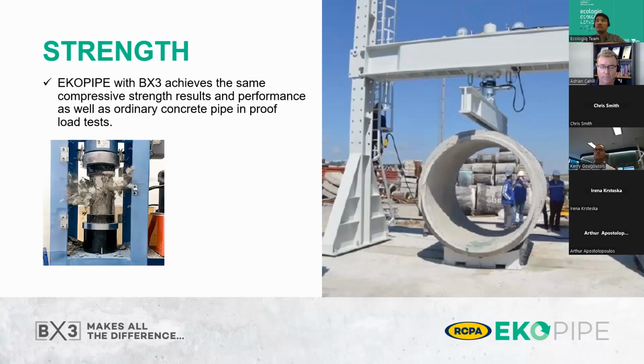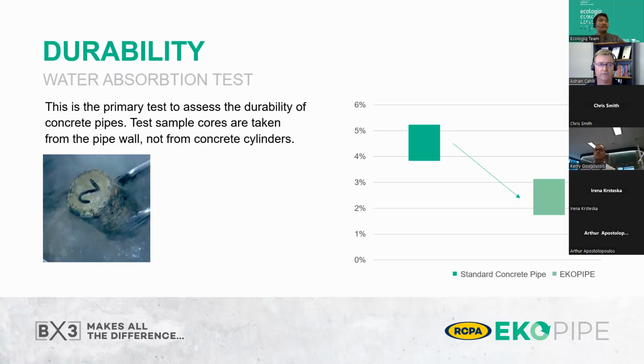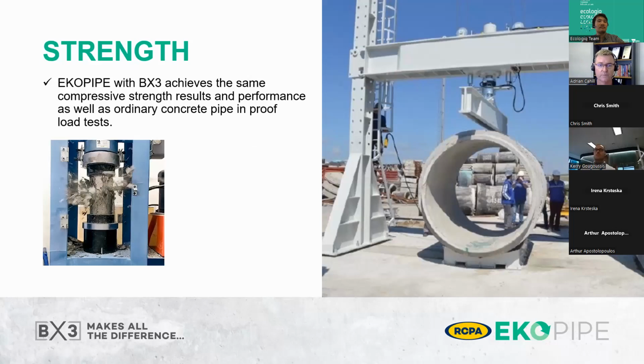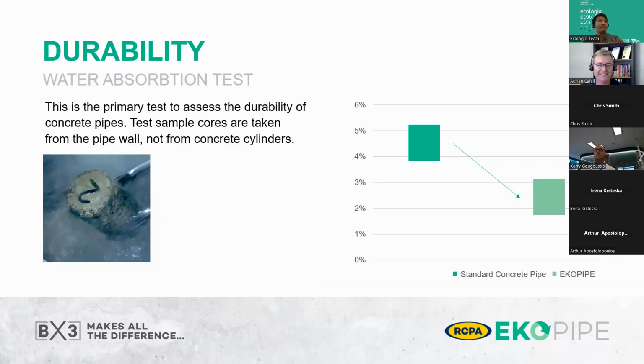That being said, RCPA does do concrete compressive strength testing of our concrete as routine QC, and EKOPipe concrete is equally as good as a standard concrete pipe. We typically run strengths in the 60 MPa territory at 28 days, and we can easily achieve that with our EKOPipe concrete. In terms of proof load testing, it's equally as good, so there's no compromise there. And now you can go next, thanks.